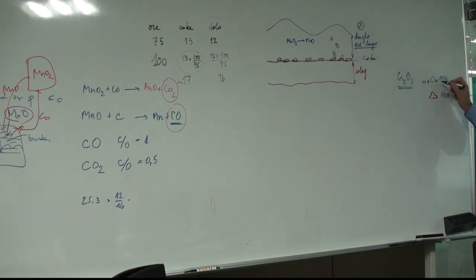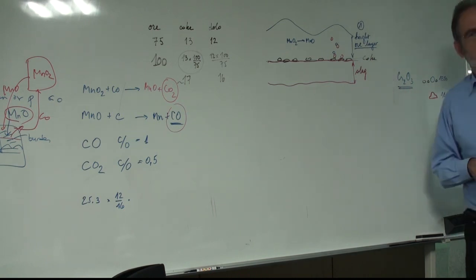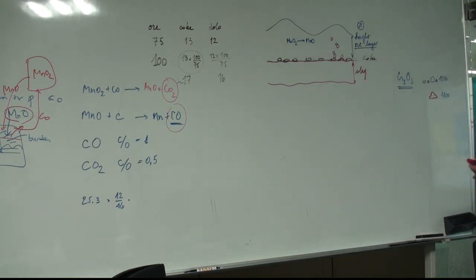But carbon does not touch. It is the CO from the carbon which reduces. And you see, at 1400 the pre-reduction began, but also melting began. And then we also destroyed the refractory of the furnace, or of the pilot.